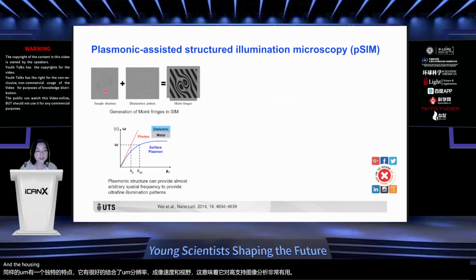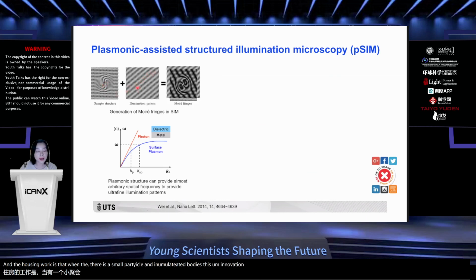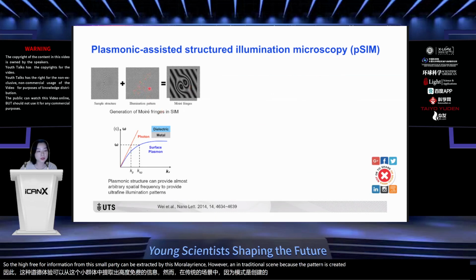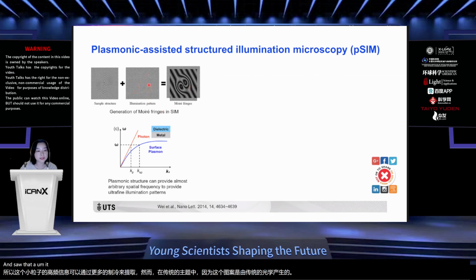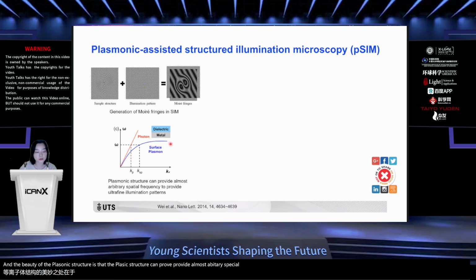So it means it's very useful for high throughput imaging analysis. How SIM works is that when there is a small particle illuminated by this illumination pattern, it will create so-called moire fringes. So the high frequency information from this small particle can be extracted by these moire fringes. However, in traditional SIM, because the pattern is created by traditional optics, it is still diffraction limited. So the resolution of conventional SIM is still not very high. And the beauty of the plasmonic structure is that it can provide almost arbitrary spatial frequency so as to provide ultra-fine illumination patterns.